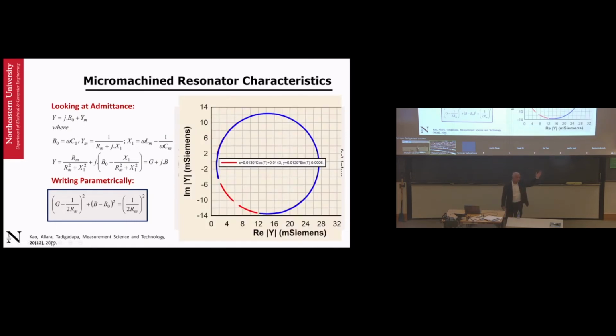And just to prove it, if you plot the real part of admittance and the imaginary part of admittance, it is an equation of a circle. There it is, okay? The blue line is the experimental data and the red line is the theory. And by this, I can actually tell you all the motional components of this device. By the way, those LCR circuit elements are not some real parts. They are coming from the material properties and the transduction, the electromechanical properties of quartz. And so you can link them all, including the dissipation, in this particular case the resistance, that is the motional resistance.